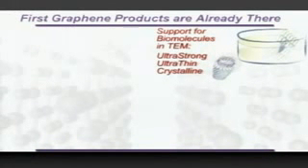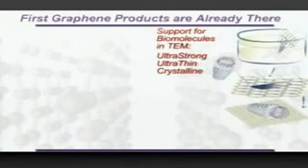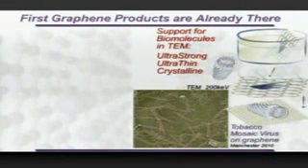But to be realistic, let me give you one example of an existing application. Graphene is an extremely mechanically strong material. It's extremely thin and it is conductive. So you can imagine it's an ideal support for any object to be observed in a transmission electron microscope, especially for biological objects. That's exactly what we did in this experiment. You take freestanding graphene, you dip it into some solution of your biomolecules, and you dry it. In this case, we used tobacco mosaic virus, and then you can observe them quite easily in your TEM. No staining, nothing is required. I know nothing about TEM or about biology, and it worked. It worked the first time immediately, and several companies now do sell it as a product.